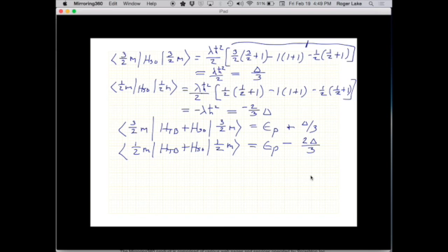So now your valence band at gamma becomes, you've got 4 states that are degenerate at EP plus delta over 3, and these are from the 3/2 states. And the 2 states down here, EP minus 2 delta over 3, are from your J equals 1/2 state. J equals 3/2 and J equals 1/2. So that's what broke your initial 6-fold degeneracy into 4 and 2.